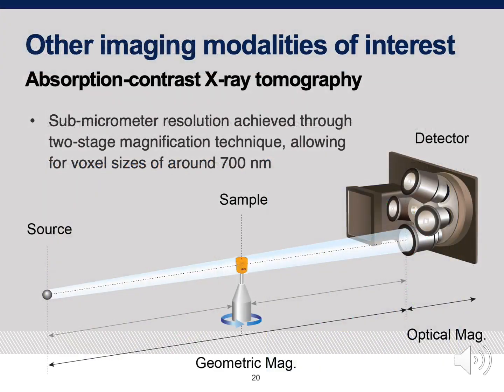On the X-ray microscope, as I've alluded to, we have other imaging modalities at our fingertips, and one of which is absorption-based tomography. And the technique is very useful in identifying density differences in our sample caused by second phase particles, as we are keenly interested in. And so the absorption tomography experiment is different here. We're focused not on the diffracted beam, but on the forward transmitted beam. You have still a divergent beam of X-rays transmitted through a rotating sample, and the transmitted X-rays on the detector are used to reconstruct the sample in 3D.